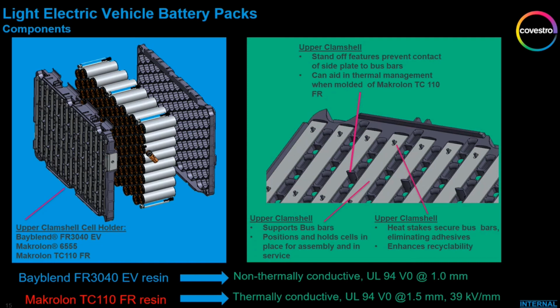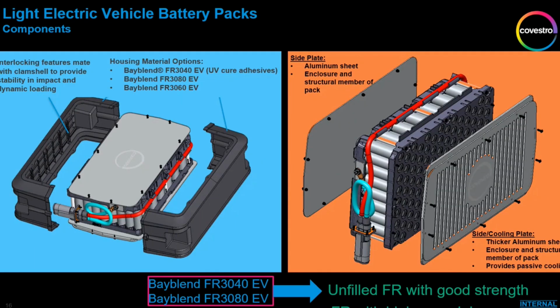Another material, as I mentioned, for thermal management is Makrolon TC110 FR. And that is a thermally conductive, flame retardant, and electrically resistant material. So it has a lot of things going on in it at one time. And this material is a good choice if you have thermal management issues and you need to be able to remove a little bit more heat from these packs. And we'll see in a moment that you do have thermal performance advantages by using a thermally conductive polycarbonate versus the non-thermally conductive Bayblend in this application.